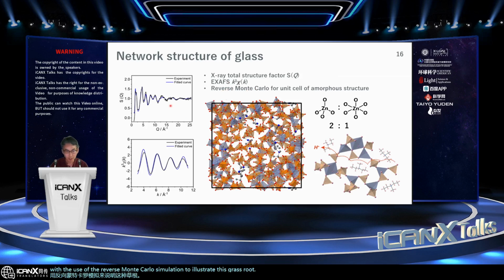Okay, and so this is the X-ray absorption fitting, and as a result, we understand that at least in this glass state, zinc forms both tetrahedral geometry and octahedral geometry to make the networked glass as shown here. Sorry, it's a bit messy, but in principle, this structure forms a three-dimensional structure from zinc and phosphates. And the ammonium cation derived from the ionic liquid is in the pore, which supports very fast proton movement in the structure.